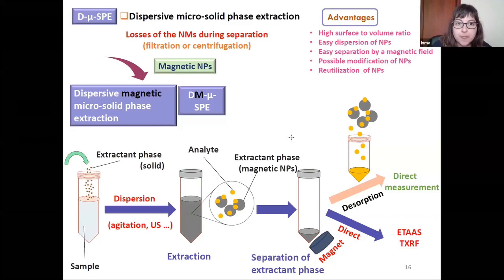First, the micro solid phase magnetite nanoparticles can be added to the sample solution, or they can be directly prepared after addition of the precursors. And after agitation or ultrasound energy application, we have the nanoparticles synthesized if we add the precursors, and also the analytes bonded to the magnetic nanoparticles. Then we have to perform the separation of the magnetic phase using an external magnetic field, as we can see here. And then we have two possibilities.